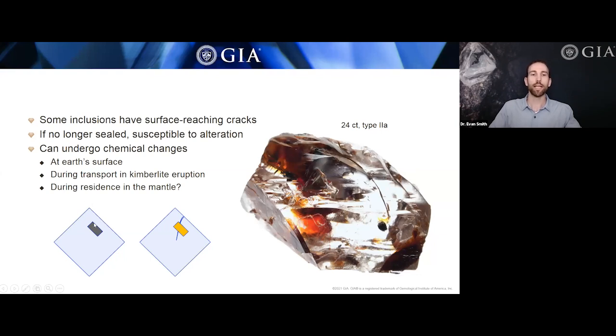So here's a diamond, and it contains a very well sealed inclusion that is sealed off from the external environment. But here's another inclusion, and it has this crack that penetrates through it and is actually surface reaching. It's reaching the surface of the diamond. And this means that it's no longer sealed. And if it's no longer sealed, then it's susceptible to alteration. So the inclusion can kind of change a bit.